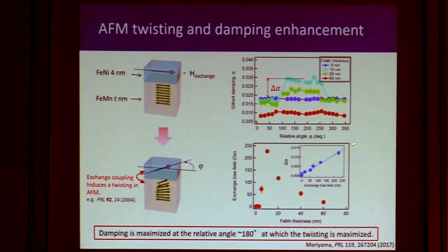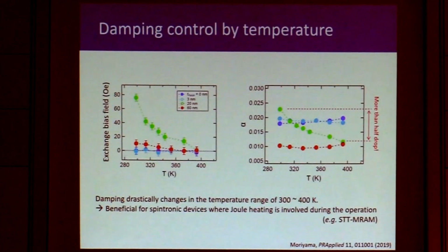So one more thing we can do from this result is, because the exchange bias field can be adjusted by the device temperature. The exchange bias is generally decreased toward the blocking temperature. So in this particular device, the exchange bias field can decrease from 80 oersted to 0 oersted in like 100K. So if you look at the damping of this device, actually the damping is reduced much. This reduction is more than half the drop.